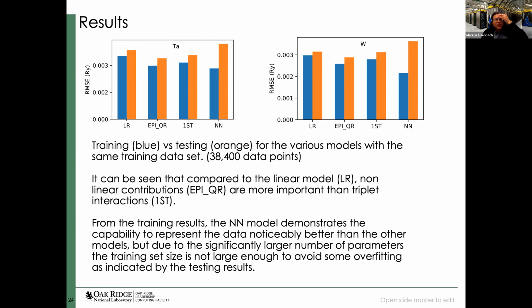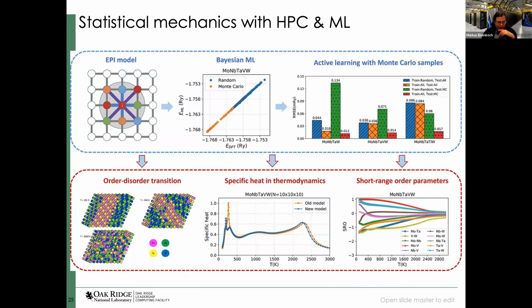So just using now this pair interaction model approach, we demonstrate a workflow that can automate the combination of first principles, machine learning, and statistical mechanics. So we start out by, again, whatever model ansatz we choose, train it on some initial randomly selected set of data, perform these Monte Carlo simulations that will explore new regions of phase space, here identified by these orange points. So in this case, especially explore some new additional low-lying energies that were not really covered in our original training set, retrain the model based on those, and